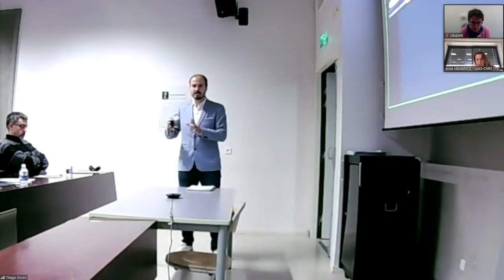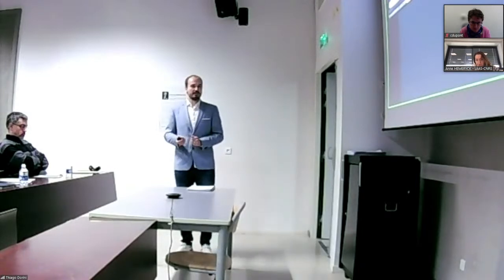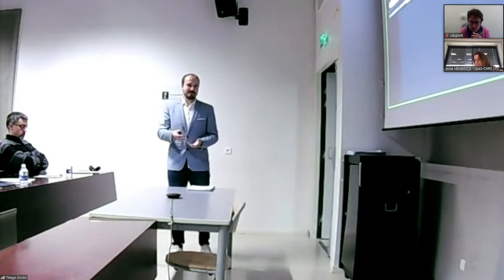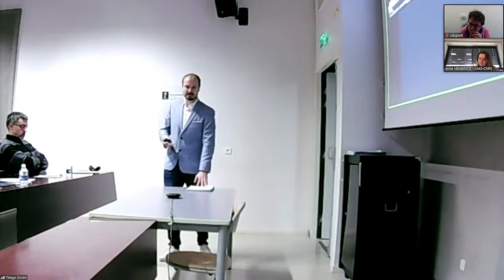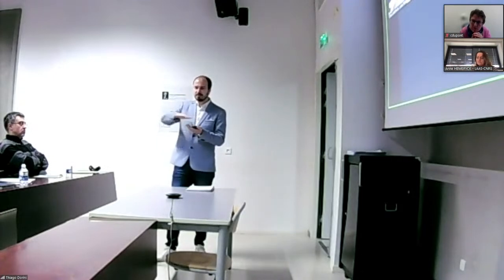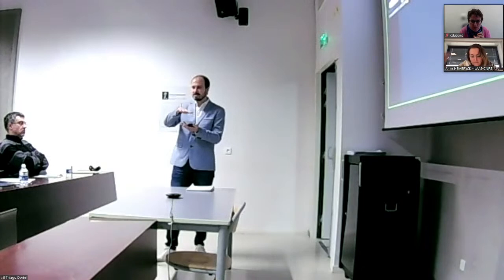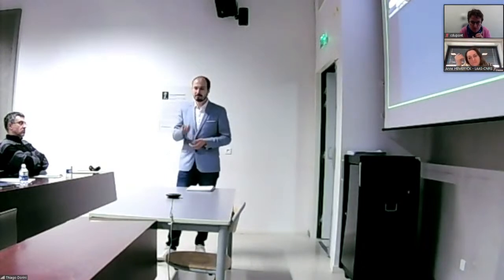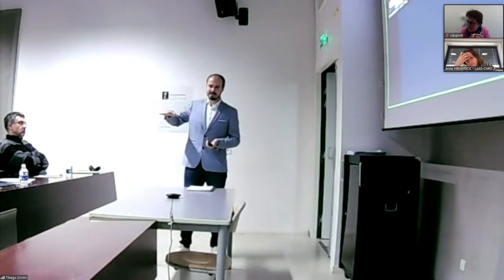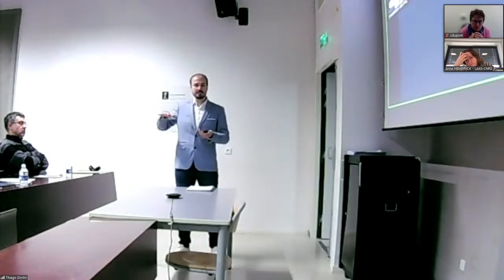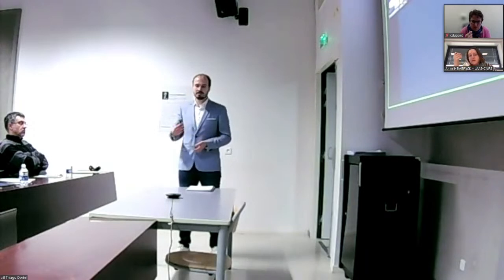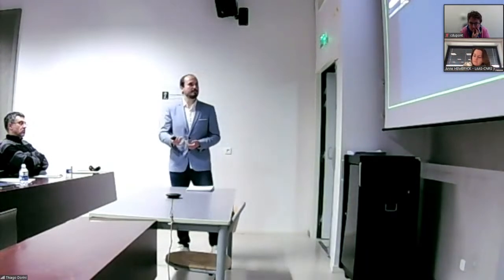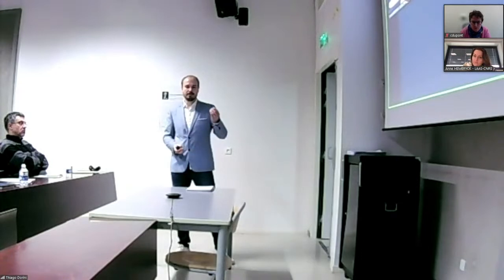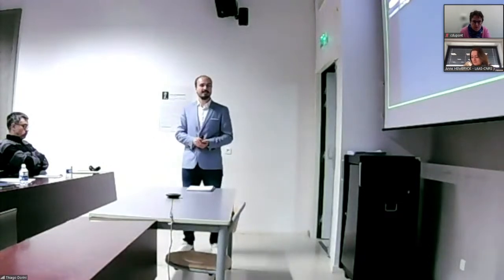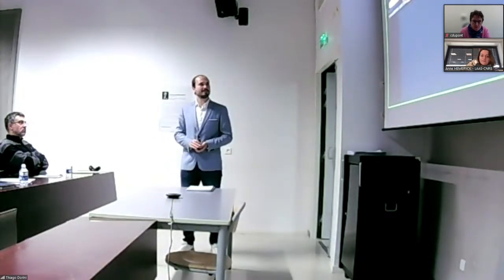So we try to be as close as possible to the experimental value. And the second thing that appears when we do this is we have another degree of freedom on how we put this oxide on the platinum substrate. For this, we have tried to simulate many different translations and rotations on these systems, and we did not find a significant difference in the total energy. So that's why I didn't discuss this in much detail in the work. Okay. Thank you, it is clear.